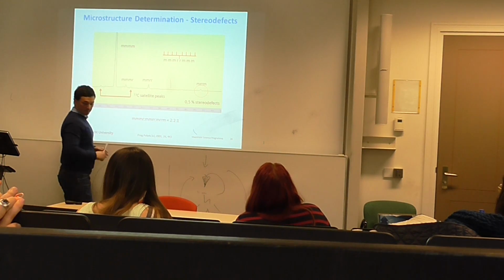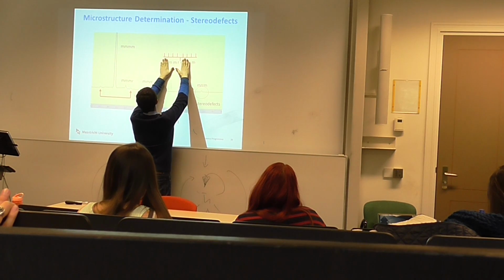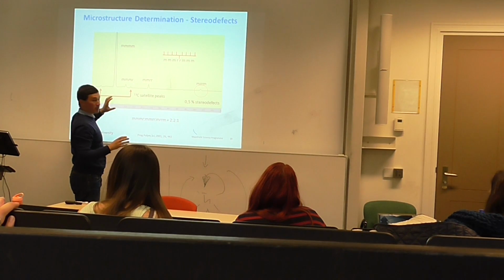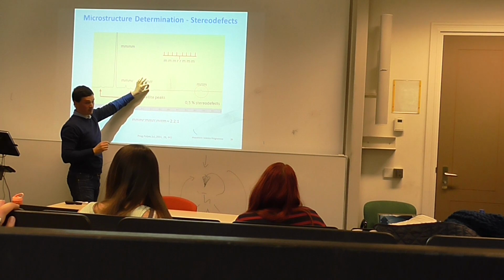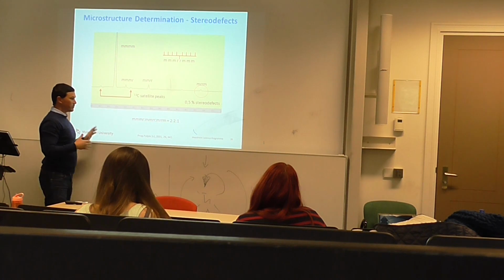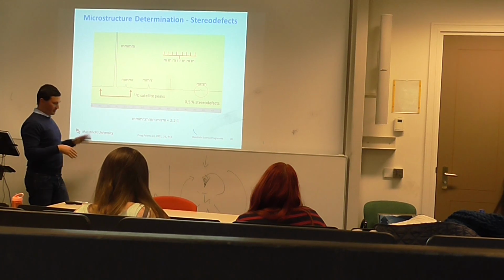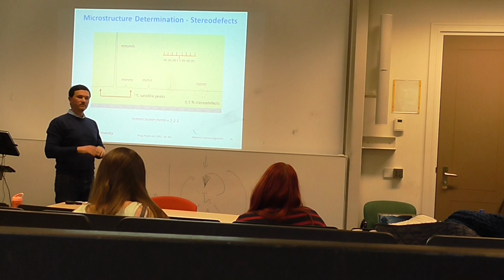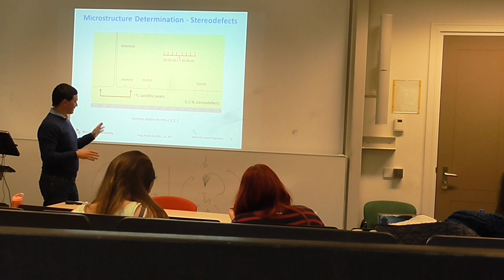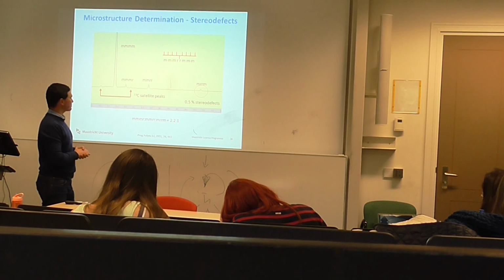So let's examine it. If you have these NMR, it will be visible here. Okay, guys, bear in mind, this is out of scale, so these are very small peaks. They can be easily confused with background noise. So the carbon-13 that we are acquiring here is very different from what you may be used to. Generally, you have to acquire lots of scans and take particular care while acquiring the spectrum. So these are generally acquired over hours, not half an hour, which generally we are used to.